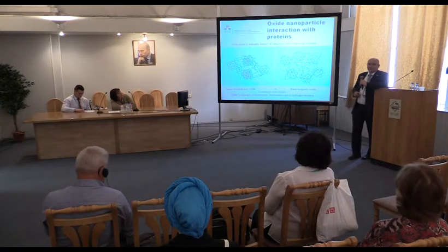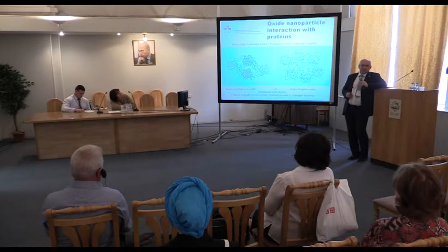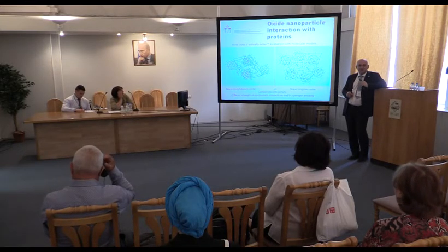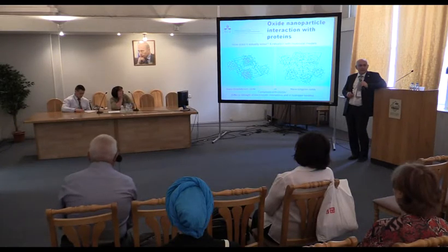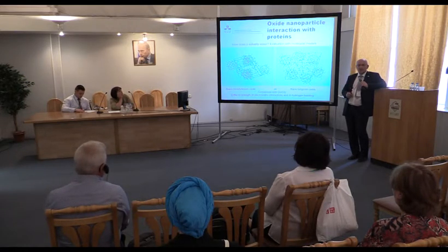And finally, what was very interesting for us was to get some direct molecular insight. How can we see what proteins are doing with nanoparticles? So what we have done, we have used nanoparticles which are stable in aqueous solution. It's so-called phosphomolybdic and phosphotungstic acid, because these anions are considered to be true ions, but they have the size of 1.04 nanometer. So these are nanoparticles in the proper sense of the word.